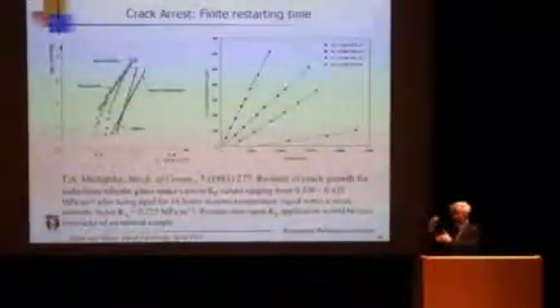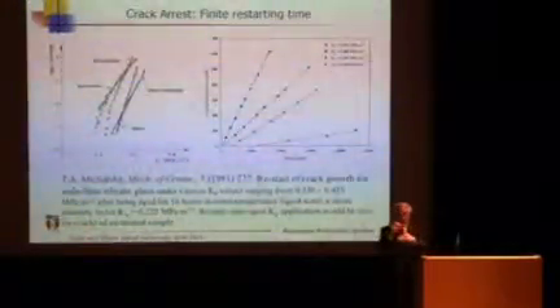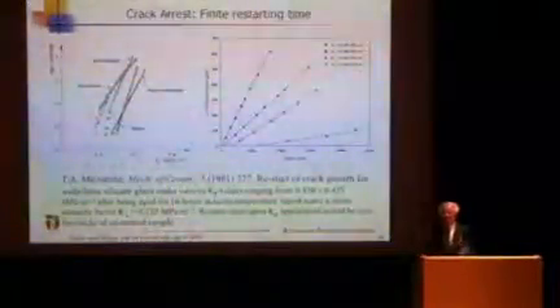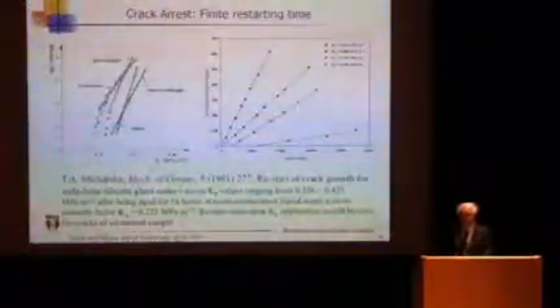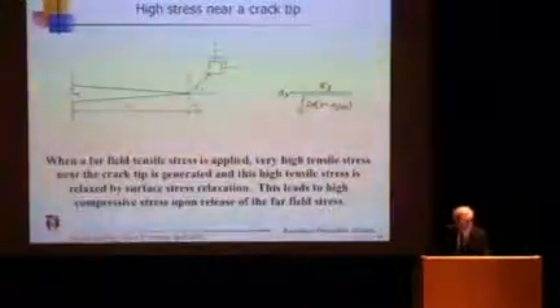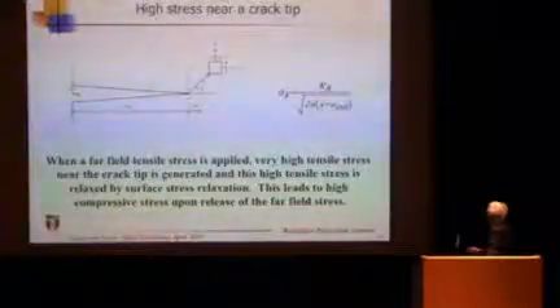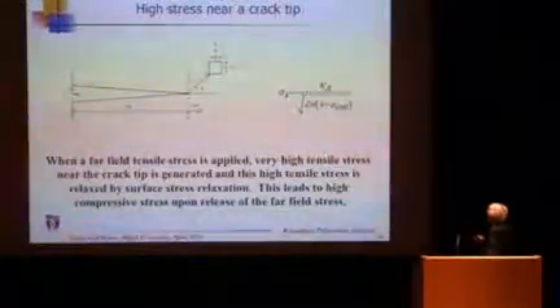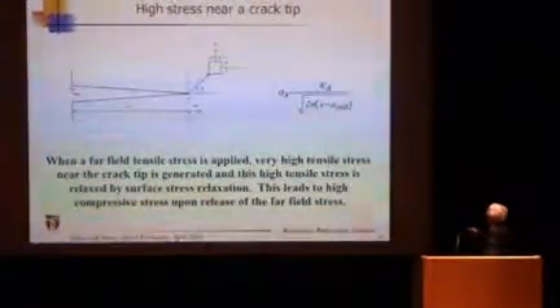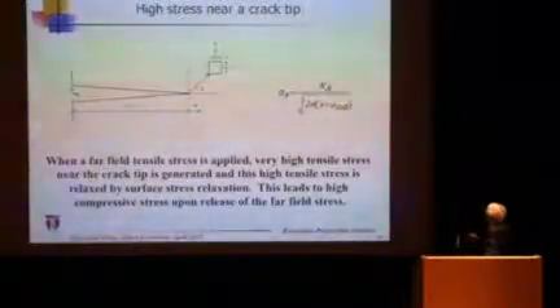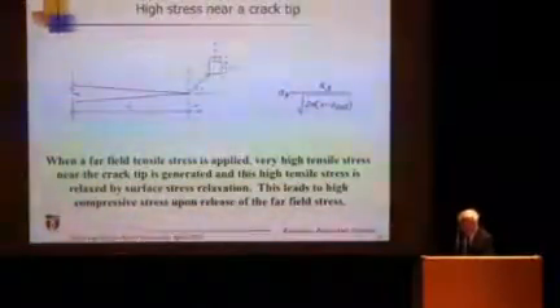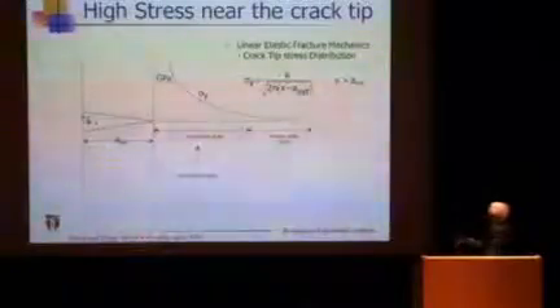But we think that while holding here, the glass experiences surface stress relaxation. You are applying small tensile stress. At the crack tip, there is high stress, and the water vapor is slowly affecting that stress profile. And that, when you let go, produces compressive stress. So this, in collaboration with a mechanical engineer, is the normal expression. When you apply uniform stress, there's a high stress on the crack tip. And that looks like this.